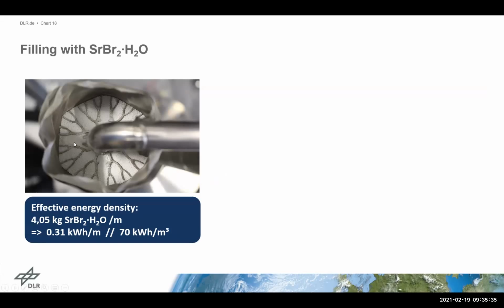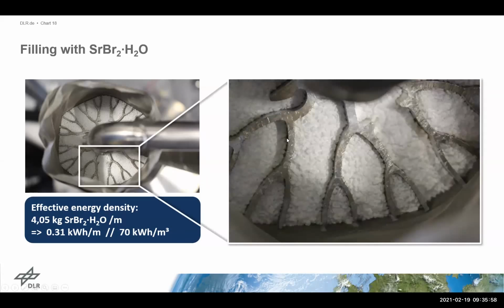And then we see here the aluminum fins, and we see this white part, which is the solid or porous material, strontium bromide. You can calculate the energy density for this unit here. This is something like 70 kilowatt hours per cubic meter. We can have something like 4 kilograms per meter of tube. And the reason why it's not that impressive: you might see here in this zoom, there is a large porosity, of course, within the bulk. And of course, this porosity has a direct impact on the energy density. So we could try to compact it, but this was not the focus of this work.